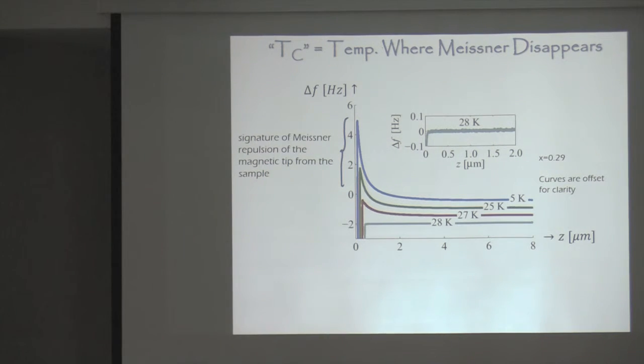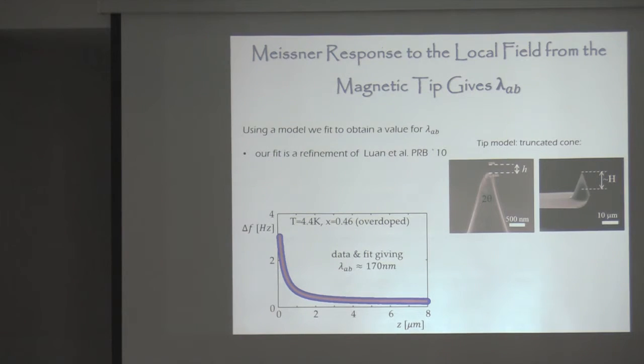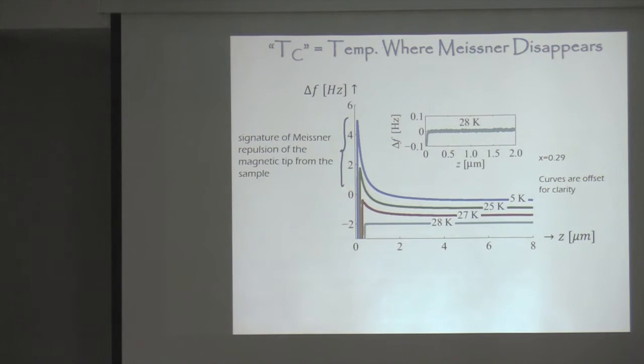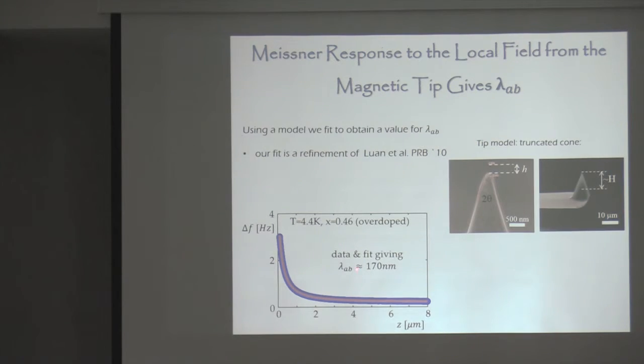Okay. What is the different asymptotic value of that? Oh, it's just an offset. It's supposed to be asymptotic to the same thing. That's one of the difficulties in temperature-dependent measurements, is that this offset sometimes shifts. Okay, so we know Tc locally, and we can fit these curves to a model, which I can detail to you later if you want, to get an estimate for the penetration depth itself.